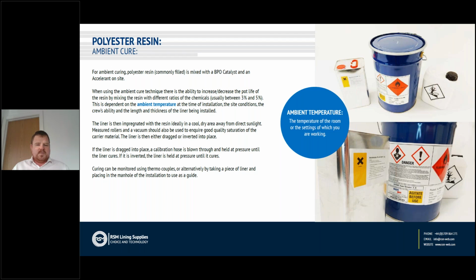Ideally, the resin needs to be kept cool in an area away from direct sunlight for the impregnation, and the impregnation should be undertaken using a vacuum and also using pressure rollers, which are specifically measured to the liner thickness being installed. Obviously, the suitability of the ambient cure process is limited because you're limited to the point of the resin's cure time. It also has less control almost because you are mixing the chemicals on site. You're not in a controlled environment, and so you need to be particularly careful or cautious about the installations you attempt using the ambient cure process.